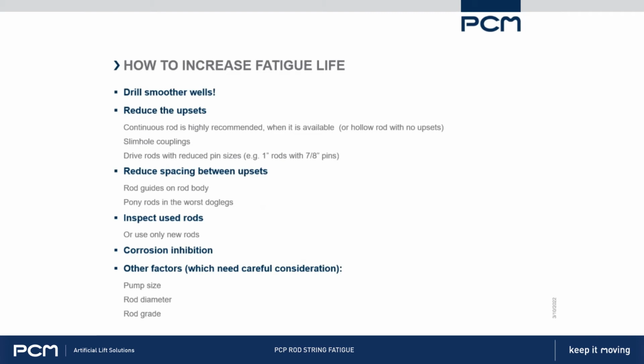Inspecting your used rods, like I said before, again, visual inspection doesn't find the cracks, but if you see something wrong in a visual inspection, you definitely want to get rid of it. But something like eddy current testing can detect cracks, and that would give you the best results. Corrosion inhibition: if you've got corrosion in your wells, if you're seeing corrosion pits on your rods when you pull them out, a corrosion inhibition program will greatly improve your fatigue life as well.